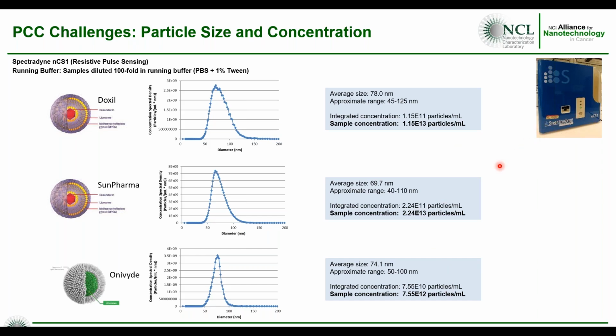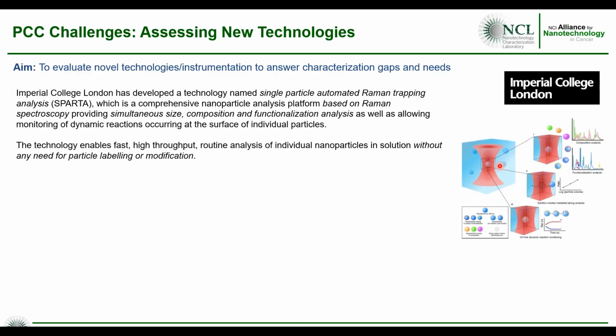So it's a good step looking at a per particle characterization, but how do we actually look at drug loading for these particles? For that, we're assessing new technologies, and we're working with 2 different groups to look at this. The first one comes by way of Imperial College, where they developed SPARTA, or single particle automated Raman trapping analysis, which can look at size, composition, and functionalization without any kind of labeling at all. And this is done on a per particle basis.